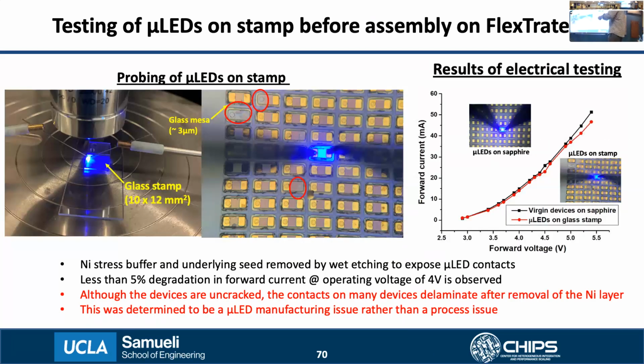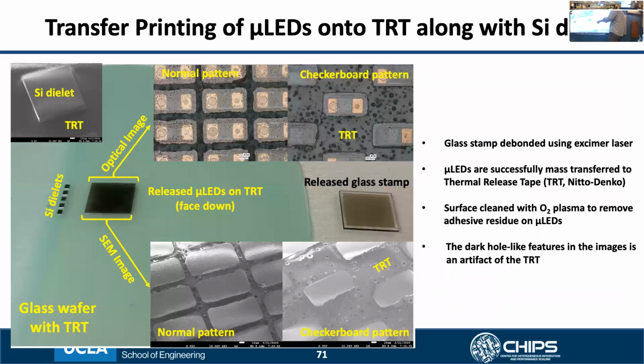So anyway, we decided to go ahead with the process to show that we can assemble these micro LEDs on PDMS. So here you see the placement of the stamp on the thermal release tape, where the LEDs have now been, if you see the center blackish region, those are the micro LEDs sitting face down on the thermal release tape after the final laser debond step. We have also flip chip bonded some silicon dielets that you can see there to demonstrate heterogeneous integration.